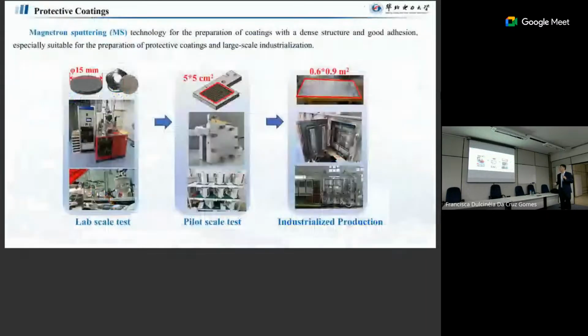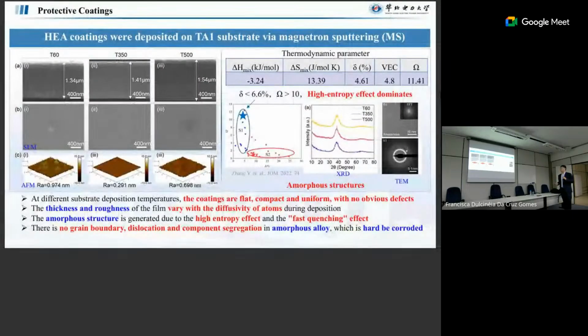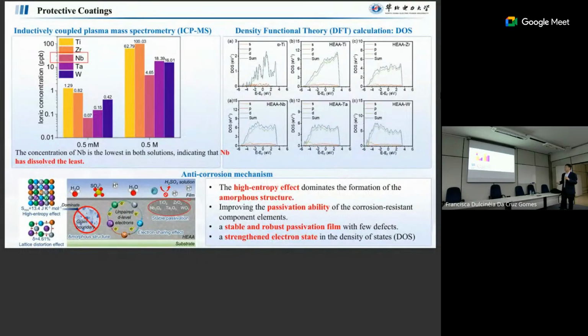Yeah. For example, in our lab, we have a lab scale test. This is for the smaller one. And also with our collaborating companies, we have the pilot scale test. Yeah, we have already industrialized. And also at CAS in Shenzhen, our collaborators have very big chambers, I think almost 1 meter wide. With this system, we can sputter to cover the surface. Yes, there are some results. I go fast. Yes, in the end, we have a good effect. It's a high entropy effect that dominates the formation of an amorphous structure, and these amorphous structures can resist corrosion.